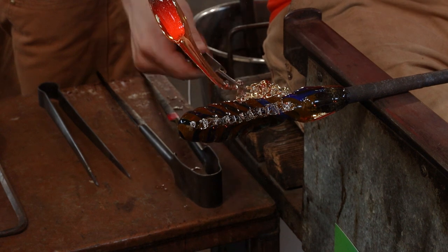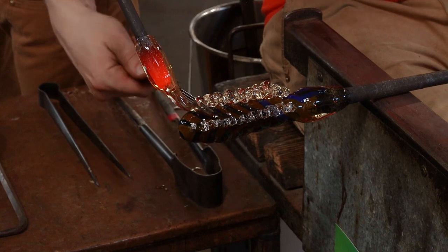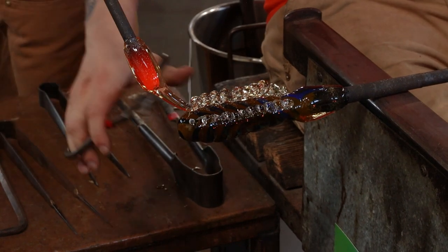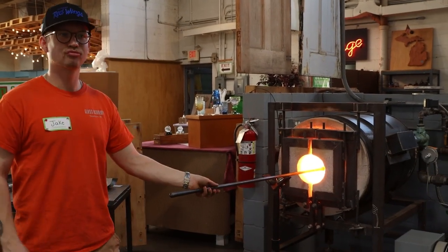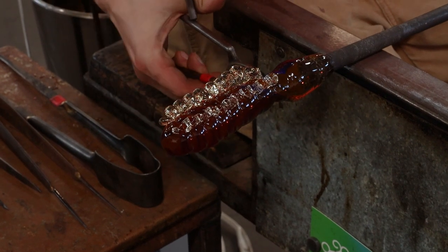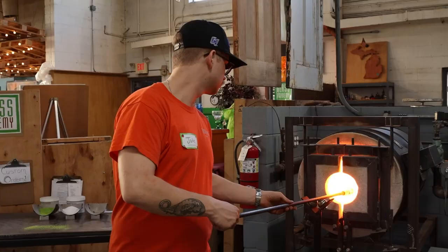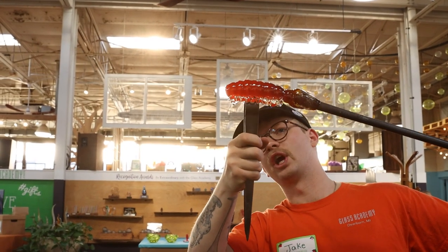You can see Michelle commented too - you see the wax coming off, you see those things smoking. There's not supposed to be wax coming off the tweezers. But for that scenario, if we were doing a production line of these, I honestly would take a pair of waxy tweezers and add wax to them so that they won't stick - because by the time you get to the fifth or sixth curl-over pinch bit with that thickness of glass, it would totally start to stick to the tweezers.